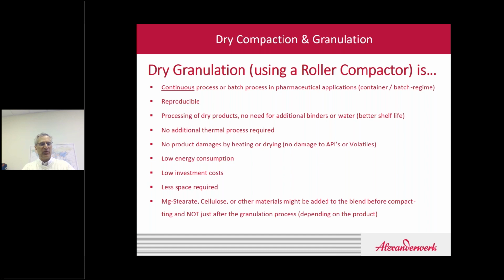Interestingly enough, doing roller compaction, you don't need any additional binders or any water or any other types of binders that may be available. It's simply a system or a technology that uses the van der Waals forces between the molecules to compress those molecules together and hold them together into a solid flake, which we then grind up into a smaller granule. Another major benefit is there's no additional thermal processing required.